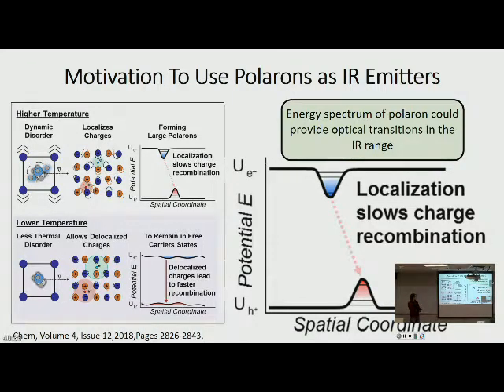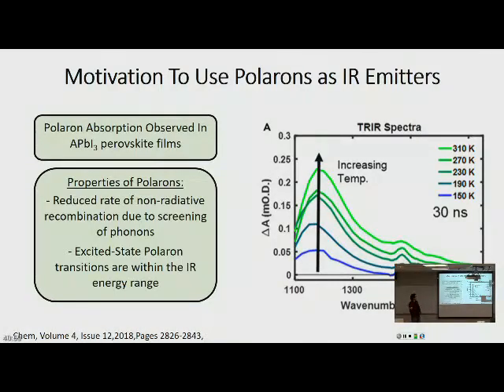And so the idea that, I guess Dimitri came up with for the NACS talk, is if you look at these energy spacings, this represents the polaron energy spectrum. This is the ground state polaron. This would be the first excited state polaron. So potentially this energy difference here could correspond to the energy needed for IR emission or transmission. And then the paper I took this from, they were looking for polaron absorption in these materials, and they saw polaron absorption at different temperatures, which is beside the point of what I'm talking about here. Basically they did see signatures of infrared absorption due to polaron, which they attribute to polaron formation.